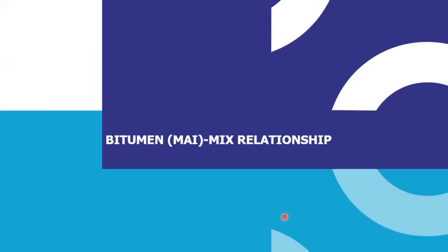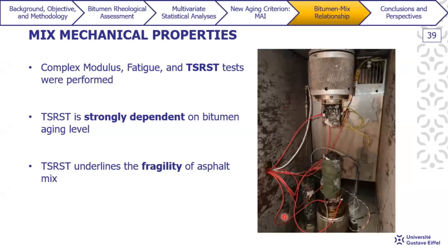Now I'm going to move on to the MAI mix relationship. To characterize our asphalt mixes, we performed complex modulus, fatigue, and thermal stress restrained specimen tests, or TSRST. TSRST is a destructive test that has been widely used to assess the low temperature performance of asphalt mix. This test is strongly dependent on bitumen aging level, and it underlines the fragility of asphalt mix, which is why TSRST was used, because it's not that common to have TSRST used to characterize asphalt mix from the base course.